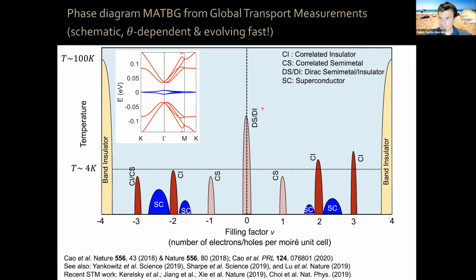obtained, as samples evolved and we got more and more data. You have a phase diagram where you have temperature here and filling factor on this axis. This filling factor is the same as charge density, which we control electronically, okay? This filling factor is telling you the number of electrons or holes that you have per Moire unit cell, okay? It turns out in these flat bands, from bottom to top, you can put up to 4 electrons per Moire unit cell.